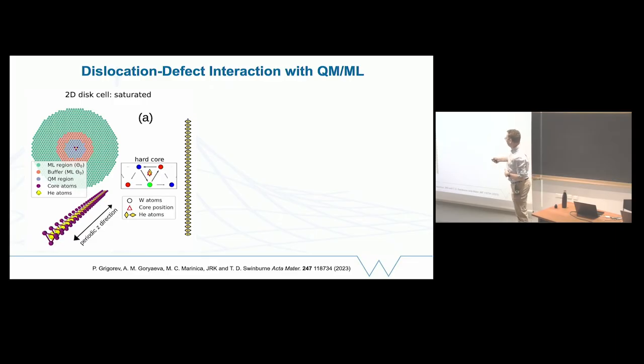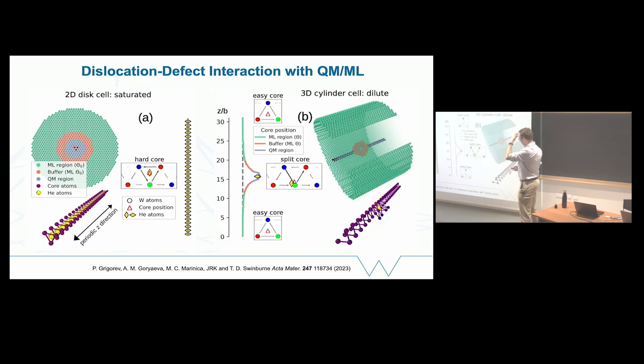So the fact that you see a change in the dislocation structure here is interesting, but maybe isn't the full story. If instead you're able to do this long dislocation core, which is now described fine by the machine learning potential, it's just the impurity part, which wasn't accurately described. We do that with quantum mechanics still. You see what you might expect, that far away from the impurity, the dislocation stays pretty much as it was before, and locally it transforms to a different kind of environment. So this was what we saw in the bulk material, the upward pointing triangle, easy core. This is the downward pointing hard core configuration, and it goes to something a bit in between. It's called the split core configuration.